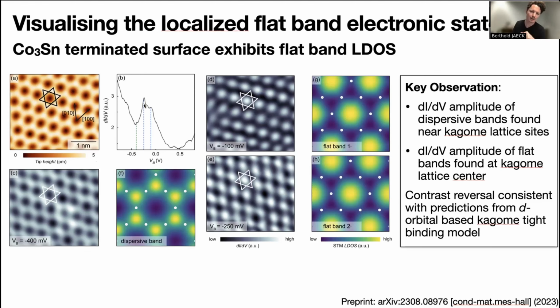Interestingly, when we now set the bias voltage to somewhere inside the flat band and then conduct these measurements, we see a contrast reversal. Instead of picking up a strong amplitude on the Kagome ring, like it was the case outside of the flat band energy, now we detect an enhanced amplitude inside the Kagome lattice honeycomb, okay? And this is quite an interesting observation.